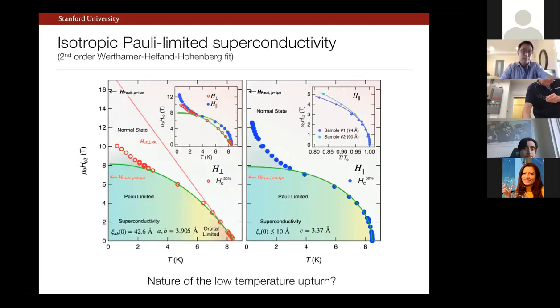So there's quite a bit to unpack here, but let me just give you the experimental survey of what we see. This is down to a leaky helium-3 system, so about 0.5 Kelvin. And so here's the raw data in circles. Okay, so this is in the perpendicular orientation. As I mentioned, it's linear approaching TC. We extract a coherence length of about 4 nanometers in this case. This is what I just described to you in the previous slide.